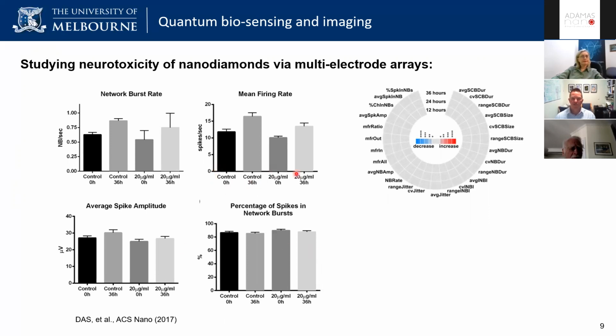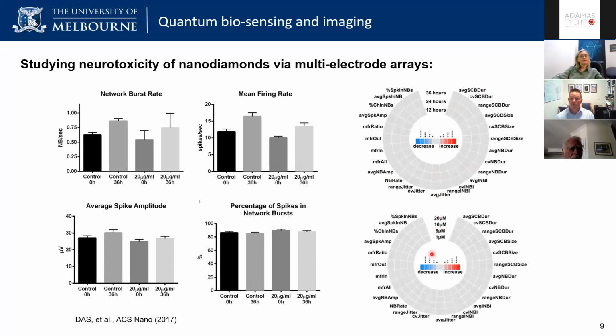And so there are a whole range of parameters that you can characterize from those raster plots. You can look at the network burst rate, the mean firing rate, the amplitude of the action potentials, the percentage of action potentials in the network bursts, all of these sorts of things. And you can characterize them before and after the addition of nanodiamond. And this plot here is showing whether there's any statistically significant difference in any of the parameters, and that will show up as a color if there's an increase in the parameter or a decrease. We looked at 28 different network parameters that are used to characterize neuronal network activity, and we didn't see any difference before or after the addition of these nanodiamonds in this system.